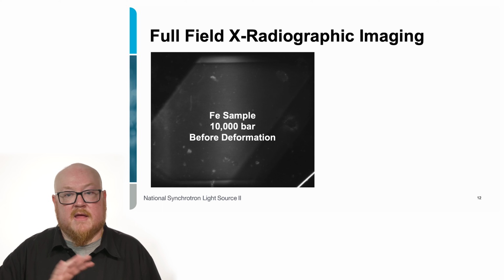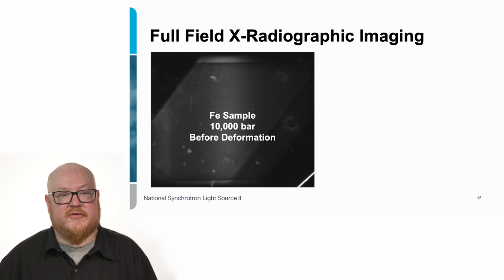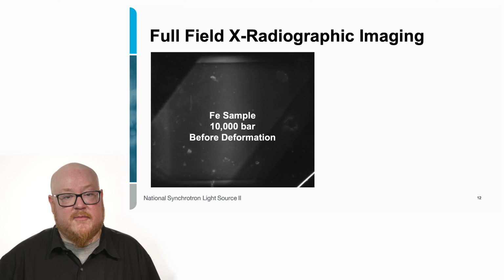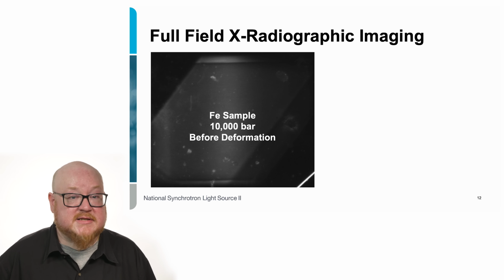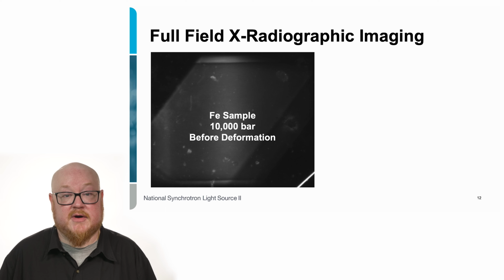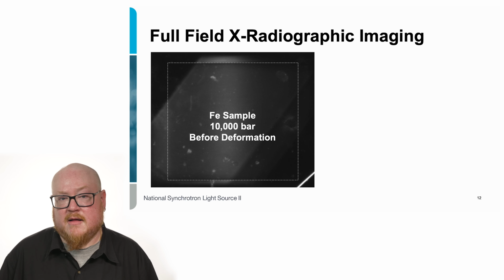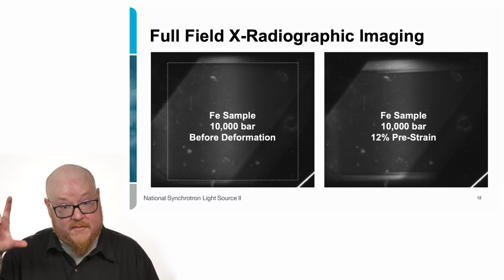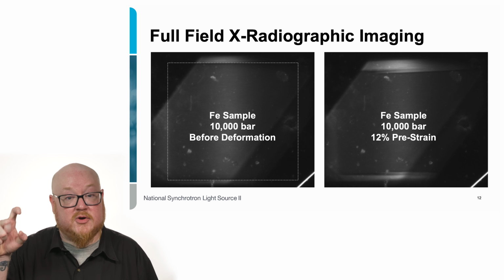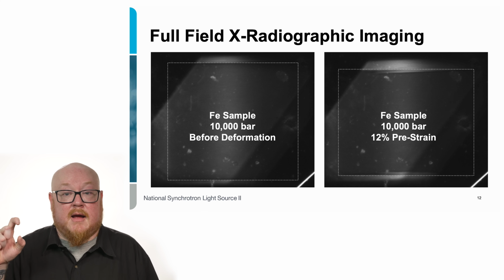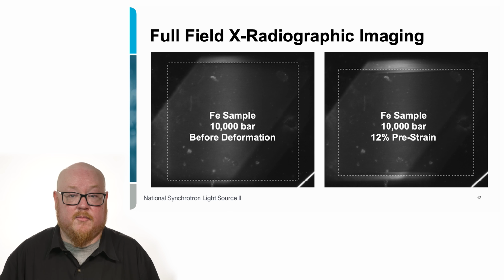But first, the X-radiographic imaging is the first thing that I want to talk about. And this here is a picture of our iron sample at 10,000 bars before we did any of the deformation to it. Now, it can be a little bit difficult to see if you're not familiar with looking at this. So what you're looking for is in this box right here. That is the iron sample right there. Okay? And then we pre-strain the sample by adding that deformation field in the particular direction that we talked about earlier. And we can see that now we have the iron sample at 10,000 bars with 12% of pre-strain.